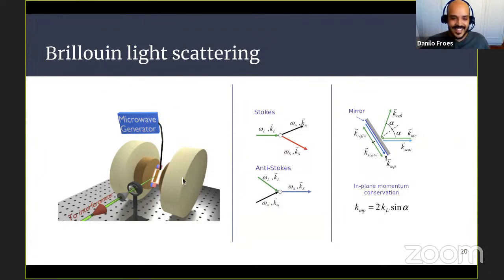The idea is having an inelastic scattering of light, where we can have these two processes, the Stokes and anti-Stokes, so a positive frequency shift and a negative frequency shift. The Brillouin light scattering experiment is done by putting a mirror behind the YIG sample, which is transparent. Due to the reflection of the wave, we can have a variation of the in-plane momentum conservation. So the excitation of the laser will have a specific K, which is proportional to the sine of alpha, the incidence angle. So we can resolve our excitation by K, so we have a K-resolved Brillouin light scattering. So this is the main idea of this.